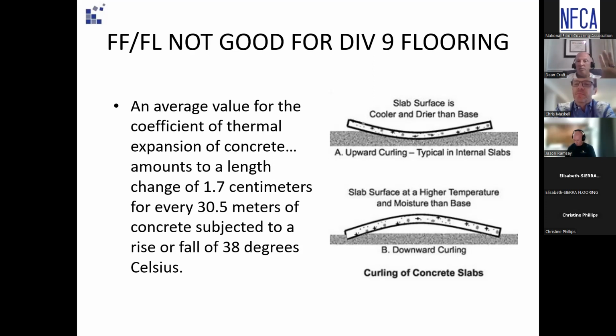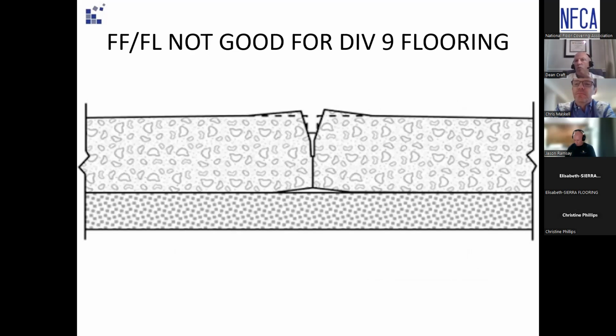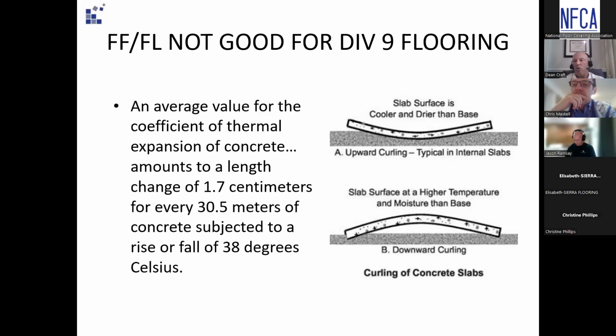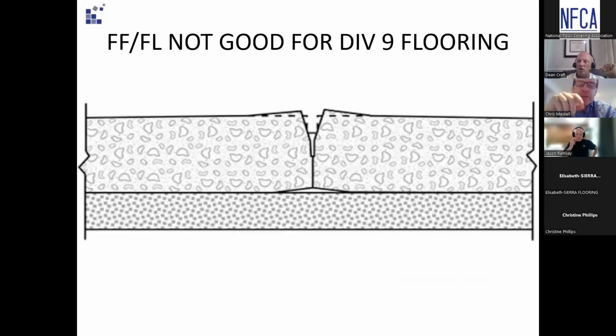This is basic mechanics of thermal contraction and expansion of concrete, also the evaporation rate. So if you come across something like the top right, and it's at a saw cut, that FFL value they did at day 3 after placement does you no good. And plus, the peak will be at a cut, and I think you said E1155 does not go across the saw cut. Yeah, it stops 2 feet from the saw cut. Right where you're going to have the most upward lifting. So a saw cut, or a moving joint.